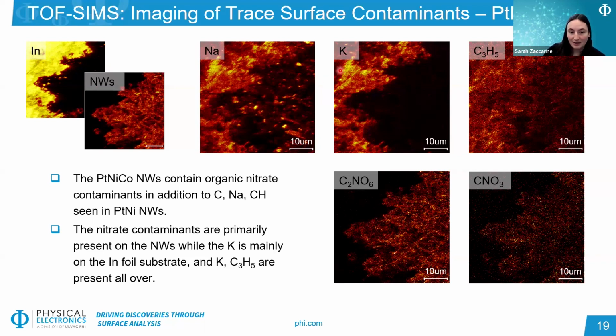If we look at the potassium by comparison, this is almost exclusively present on the indium foil, and this more organic carbon-based species is kind of present throughout. In this sample set, we also had some nitrate-containing species, which track more consistently with the nanowire area, as well as the nanowire positions, which again could mean that this is more present on the nanowire samples themselves.